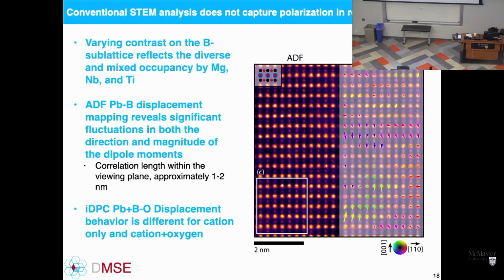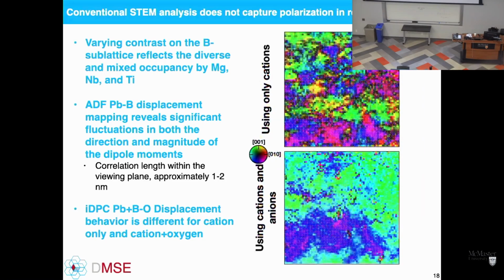And so going on to other techniques like combining that with integrated differential phase contrast, you could measure out where your oxygen positions were, but then if you compared polar maps from the cations versus cations and anions, you get very different results.